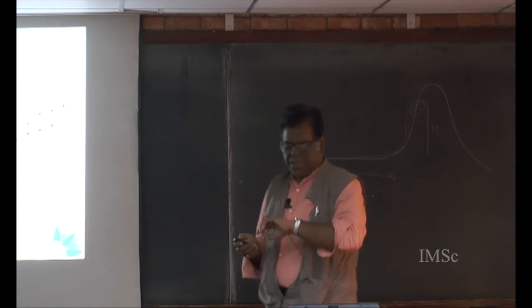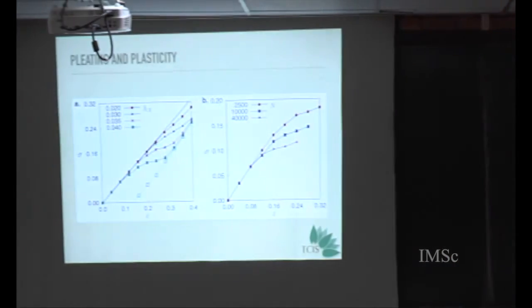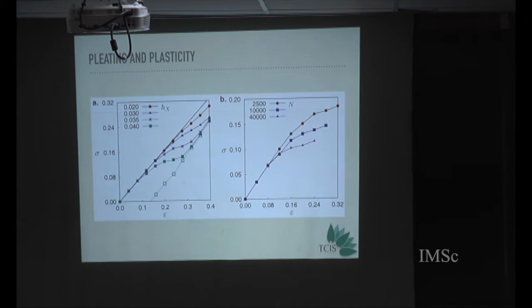So what is the connection between pleating and plasticity? I mean, the rest of the talk will go very fast, I assure. If you plot stress versus strain, then this pleating transition is exactly the origin of plastic irreversibility in this system. As soon as the network pleats, you get a flattening of the stress versus strain curve, and if you release the strain, it does not follow the same stress. So it follows a different curve.